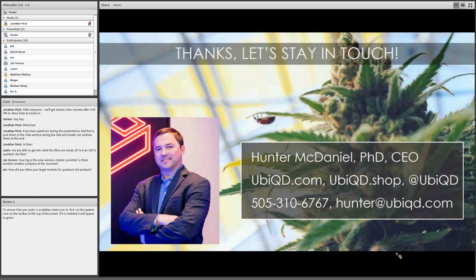Justin was asking about whether you are able to get into what the films are made of. Is it 100% quantum dot film? No. There are various reasons why you couldn't make a pure quantum dot film, or why you wouldn't want to. These are typically on the order of 3 to 6% by weight quantum dots, and it's an acrylate. I can't go into the exact type of polymer, but it's not too different from a polyvinyl butyral or a polymethyl methacrylate. It's obviously not those two, which are common.